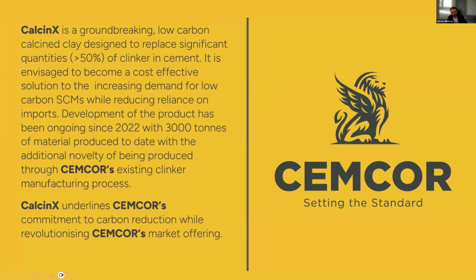So CalcinX for us is a groundbreaking development for the industry. It's essentially a low carbon clinker alternative, and we're the first cement company in the UK and Ireland to have done any real meaningful work at great scale with this. We're able to take waste materials that are available locally to us, waste clays, low grade materials that aren't useful for aggregates or cement manufacturing, and repurpose these materials in a manner that creates a cost-effective solution for alternative cements and supplementary cementitious materials. Most importantly for us, that's reducing the reliance on imports.